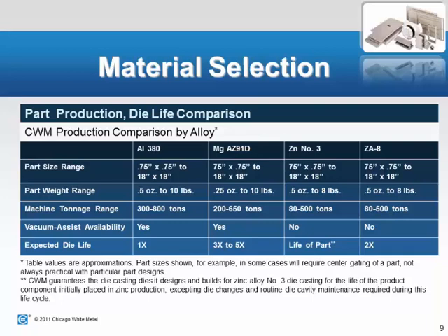The zinc family of alloys, we highlight here zinc number 3. Some people will also hear these referred to as Zamac. That's a kind of a trade name of the zinc family of alloys. You'll hear Zamac 3, 5, 7. We highlight number 3. We also use another couple of those alloys, but number 3 is kind of the most used of the alloys. Zinc is the heaviest of all the die-cast alloys. It's about 2.5 times that of aluminum. So you can see it's a pretty heavy